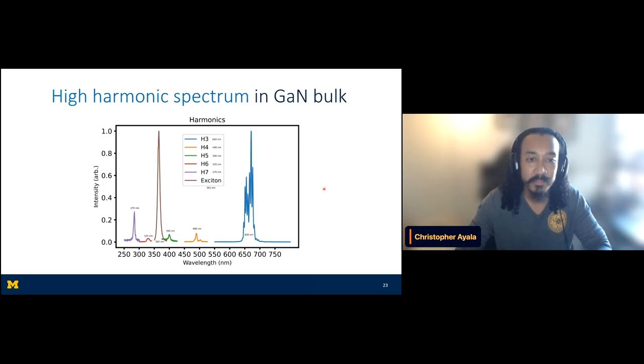With this two-color system, we were able to observe all generated harmonics from the third in the visible down to the seventh at near UV, with the harmonics being approximately 280 nanometers. What you may notice here is this really tall brown peak, and this is what I had referred to earlier as the exciton photoluminescence. In this case, when the excitons are recombining, they are forming near the band energy, which is what you see here. And photoluminescence, in a sense, is just the incoherent emission of light. That's why it's alongside all the other orders of harmonics.